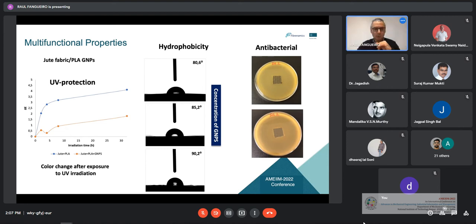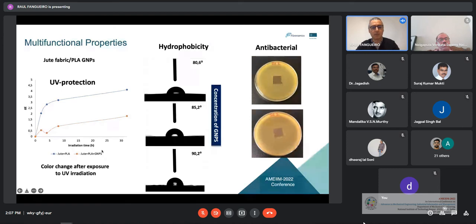And we can give this UV protection characteristic also, because graphene is working as a very interesting UV blocking material. As you can see here, we have the fibers with just PLA in blue, and then when we are adding the graphene nanoplatelets, we can reduce a lot and increase the UV protection of the material.